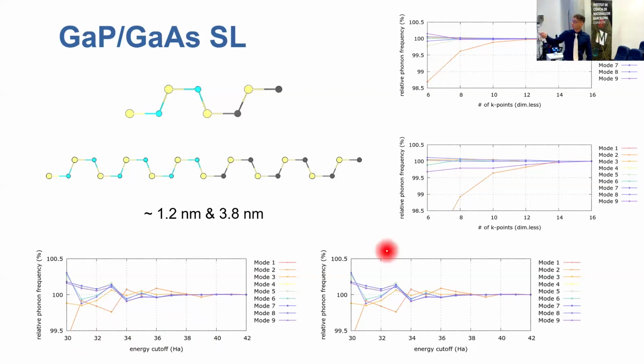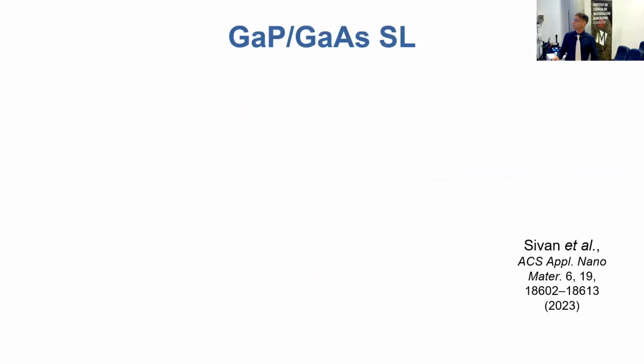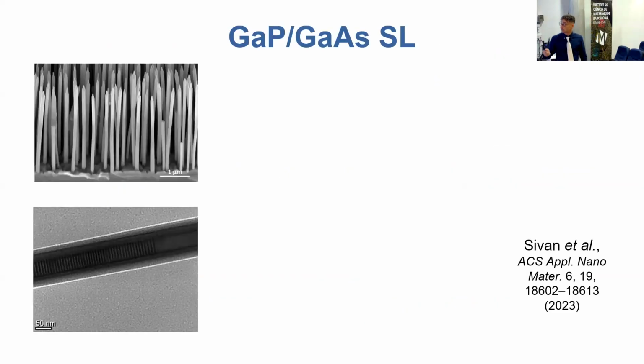Here you can see in the plot the relative phonon frequency with respect to their value at the highest resolution we could simulate, both as a function of the number of K points and as a function of the energy cutoff. You can appreciate that we already reached a very fair degree of accuracy at 8 K points to describe the Brillouin zone and 37 Hartree as the energy cutoff for the plane wave basis. So we adopted this convergence setup for our further simulations, and we computed the Raman spectra of the gallium arsenide, gallium phosphide superlattice.